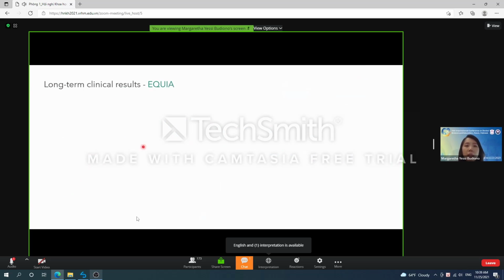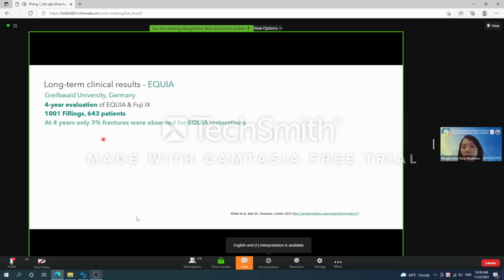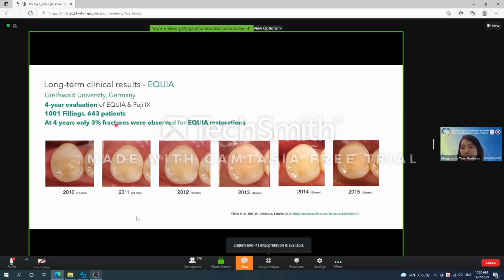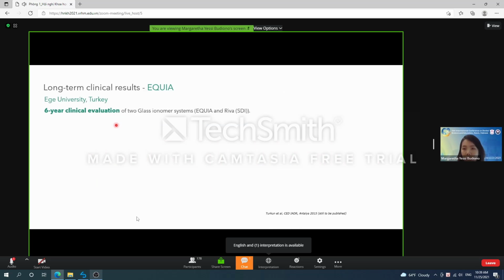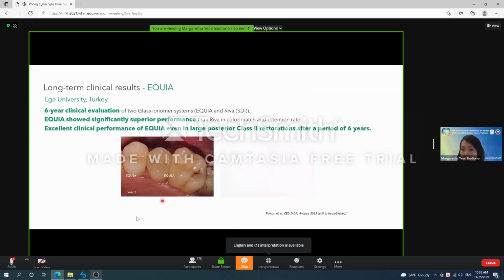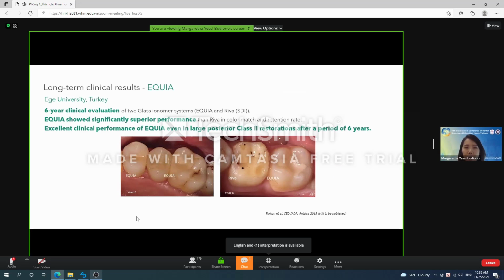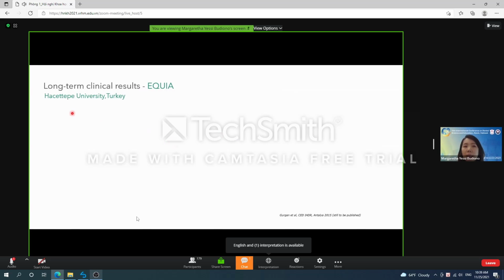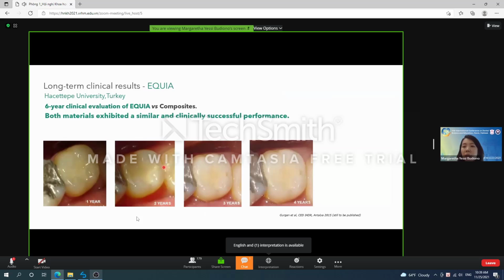So for example, this is one of the studies done by a university, a 4-year evaluation comparing EQUIA and conventional GIC on a total of 1,000 fillings. It showed that EQUIA has a lower failure rate at only 3% compared to conventional GIC. And one other study by a university in Turkey also showed that within a 6-year evaluation period, EQUIA showed better retention rate than conventional GICs. Okay? But what is more interesting is that this 6-year evaluation study proved that EQUIA has actually a similar clinically successful performance compared to composite restorations.